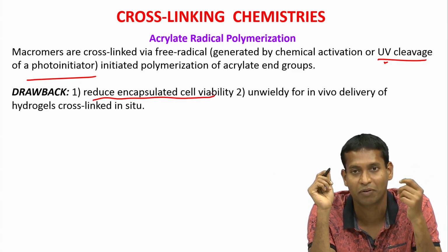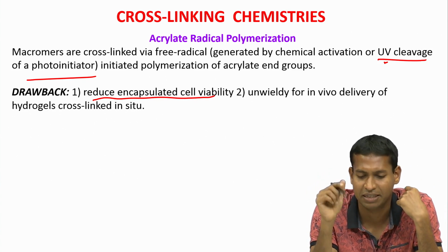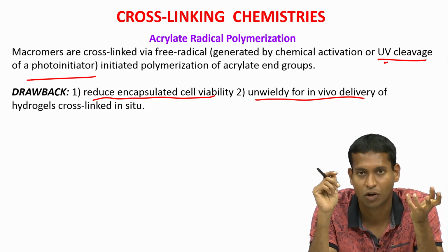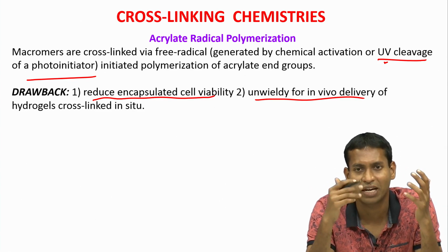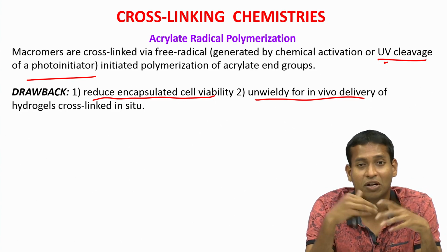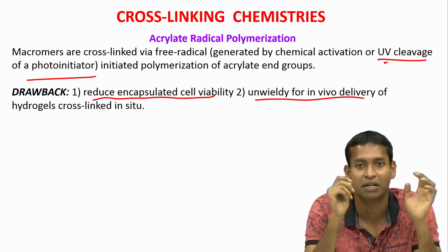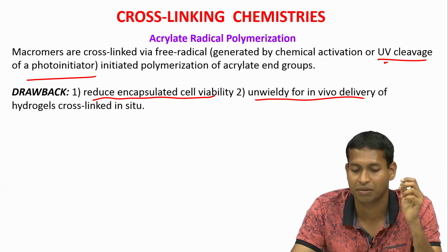So, that is a problem that was identified with acrylates for quite a bit of time, and it is not really very conducive to do an in situ delivery, and we will talk about that. It does not really happen very fast. The reaction is very slow, and if you inject it, let us say it takes 30 minutes, then in 30 minutes all your hydrogel components will get diffused out into your body, and it really will not form a depot at the site you are injecting it at.